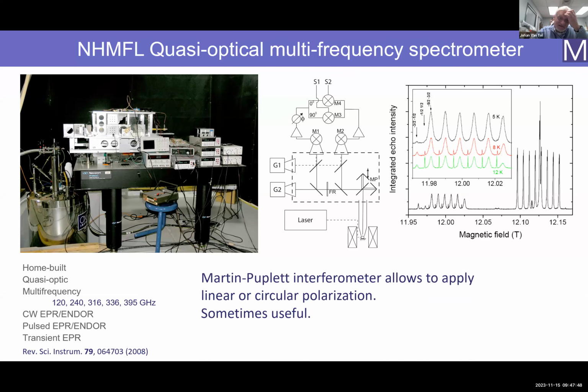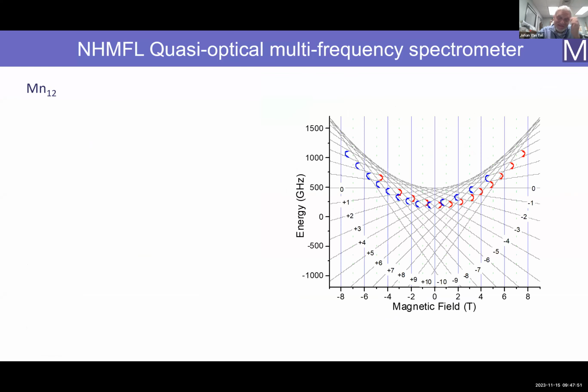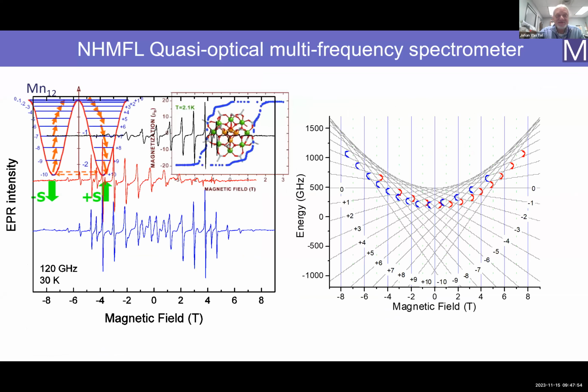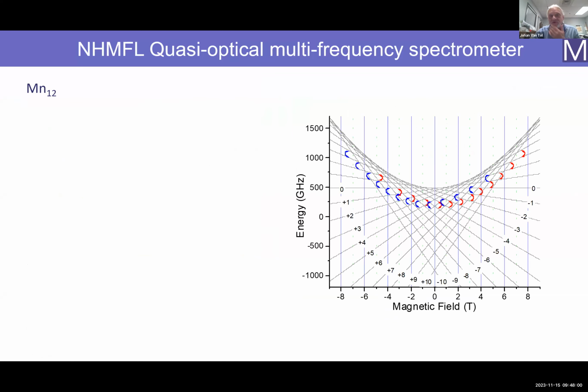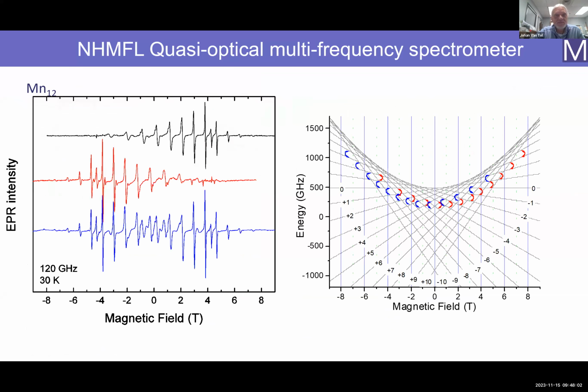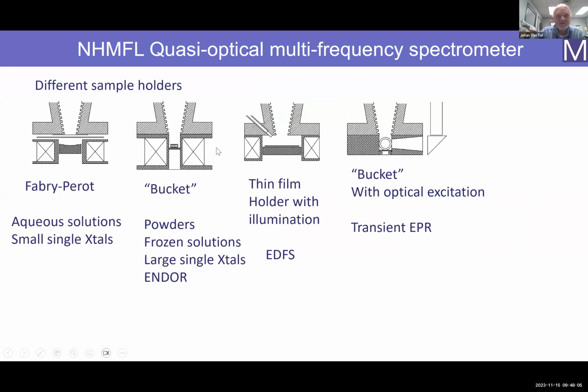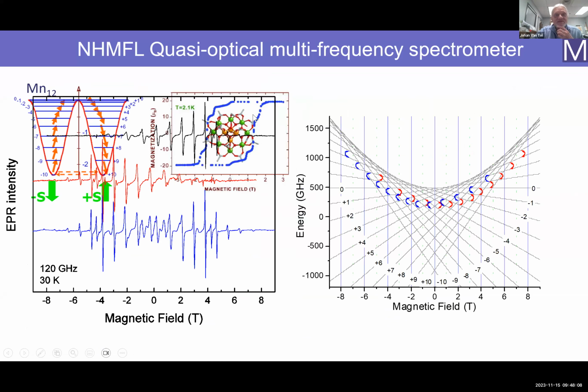So with the Martin-Puplett, there is one interesting thing that you can do with this polarization. So if you're looking at manganese 12, I wish I had tested this earlier. The manganese 12 is a molecule here that behaves like a small ferromagnet at low temperatures. You can get this hysteresis curve in the magnetization. And you have all these different transitions.